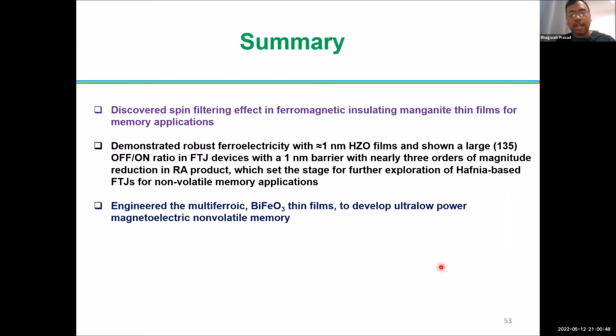Okay, so with this, I would like to summarize my talk. I have shown that we have discovered the spin filtering effect in ferromagnetic insulating thin films, and that can be useful for memory applications. In the second part of my talk, we have shown how one can achieve robust ferroelectricity in HZO all the way down to 1 nanometer, and we showed a large on-to-off ratio when we make 1 nanometer barrier FTJ devices, and we believe that if you do more research, this Hafnia-based FTJ can be useful for non-volatile memory applications.